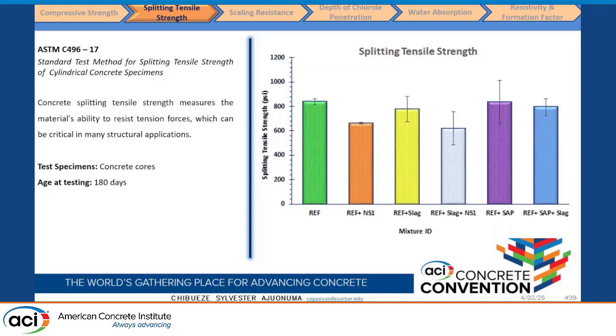For splitting tensile strength, we tested at 180 days, and we had a similar trend as we observed with the compressive strength, a slight reduction. And since we tested at 180 days, the mixture with slag also showed an improvement in the tensile strength, as well as the combination of SAP and slag.